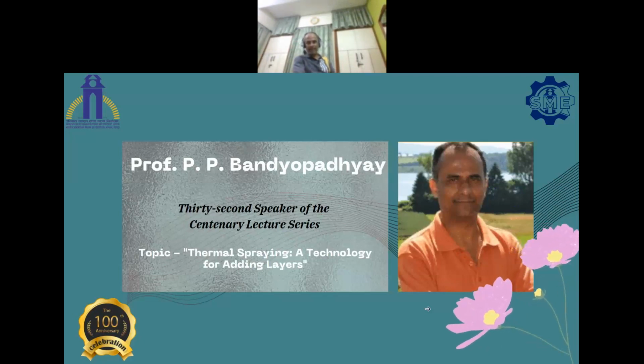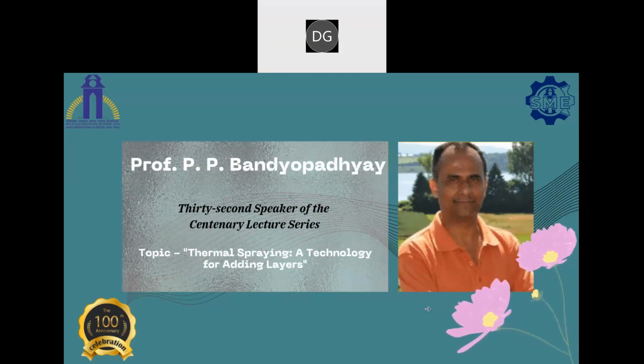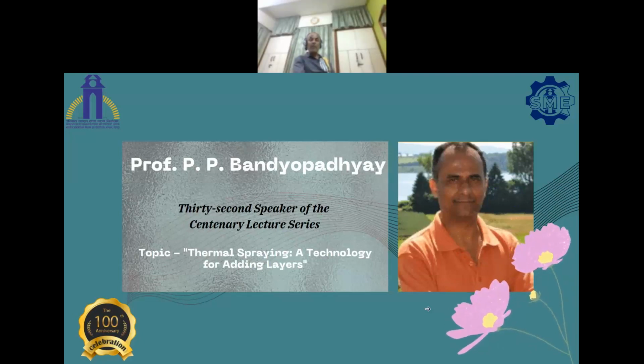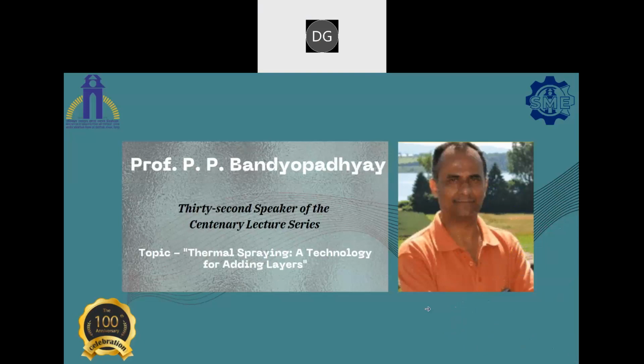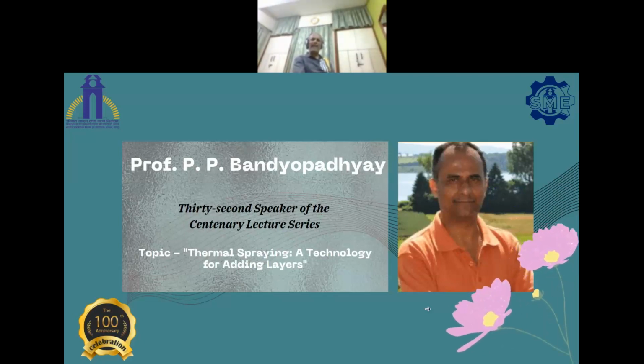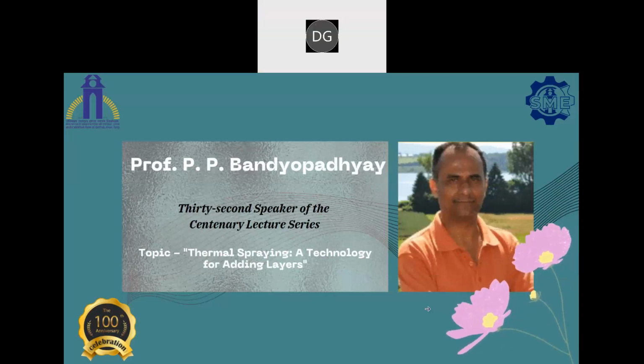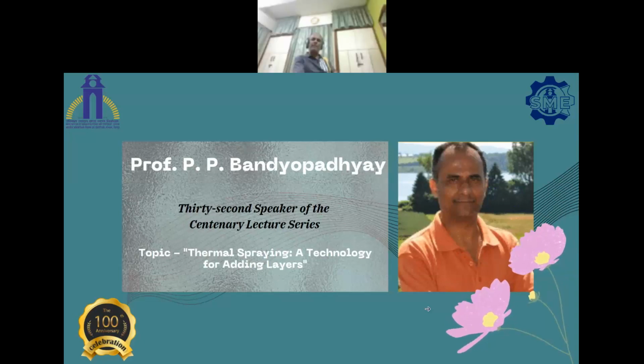So there must be limitations when you select the pairs. Of course, that's why we bring in bond coats. Sometimes one bond coat doesn't serve the purpose. For example, you take turbine blades. Initially, you have a nickel layer. Onto that, you have a chromium-based bond coat. Onto that, you have an aluminum oxide bond coat. Onto that, you put stabilized zirconia for different reasons. One is the thermal expansion coefficient. Another is to reduce the chemical gradient because oxidation of the bond coat occurs and the oxidation products are more compatible with alumina than with zirconia. So we put a thin layer of alumina as well. So we can have multiple bond coats.